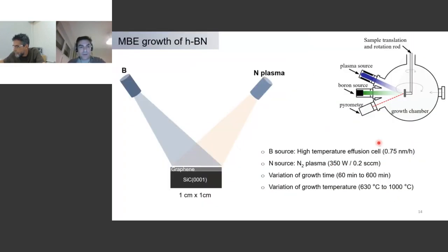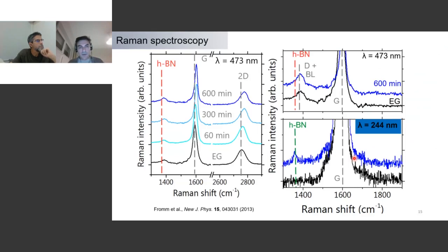So then we go for hBN growth by using MBE. And essentially, as I already explained, we have sources for boron and nitrogen. These are the conditions I use here. I don't go into detail, but you can find that in some of our publications. But we vary growth temperatures. Basically, you are turning the knobs there in order to improve your growth, or in order to get some systematics, understand what's happening. So we first take the samples out and characterize them by Raman spectroscopy.